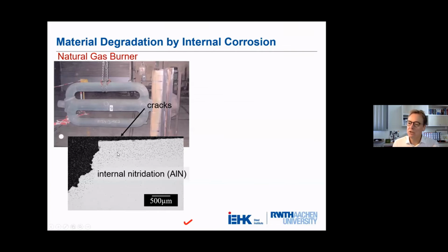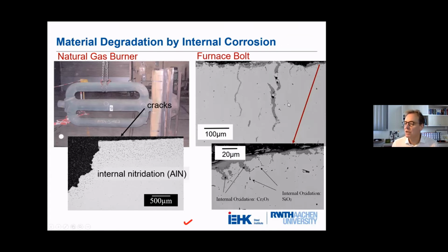When we had a look at these cracks, we found a massive internal nitridation attack of 0.5 millimeter. Obviously, the chromia scale was not able to protect this material. The second example is a furnace bolt, probably damaged due to overheating, where we can see massive internal oxidation, intergranular oxidation attack by internal chromia and internal oxidation by silicon.